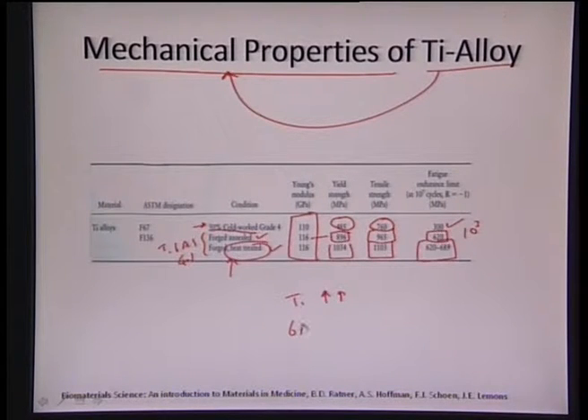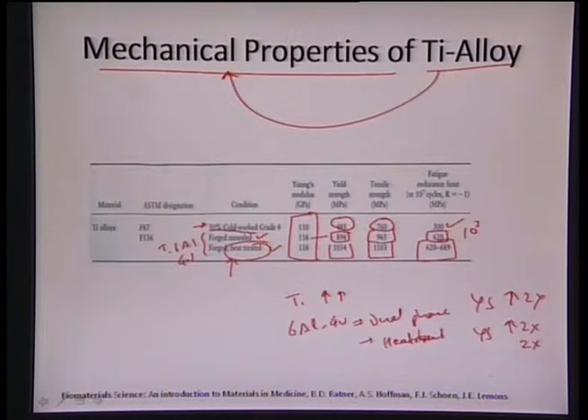Once we add 6 aluminum 4 vanadium, we see a dual phase microstructure, and that dual phase microstructure assists in the increase of yield strength, which is almost 2 times. And then controlled heat treatment can again increase the yield strength by a similar factor, and the fatigue endurance limit can also be increased by around 2 times. So that is the way in which we can manipulate the properties of titanium alloy via certain secondary additions, as well as by performing heat treatment of the titanium alloy.